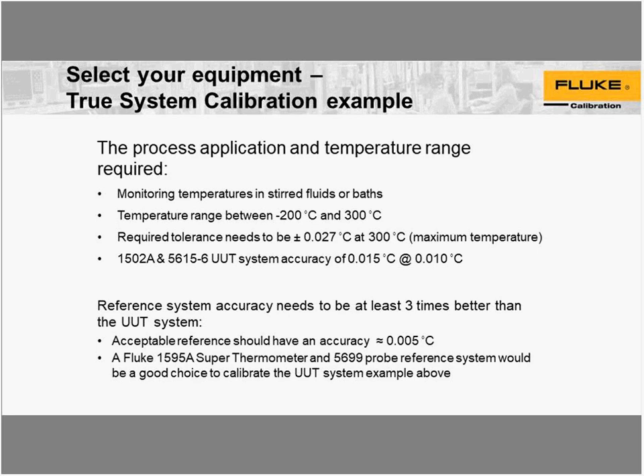Another thing we need to look at is the reference systems that you're using need to be at least 3 times better than the UUT system. So for this particular item at 0 degrees, we would like to have it at least 0.005 degrees, 5 millidegrees. So what we're going to use is a Fluke 1595A super thermometer and a 5699 thermometer probe, which is a platinum resistance thermometer. The system would have a combined uncertainty of 5 millidegrees.